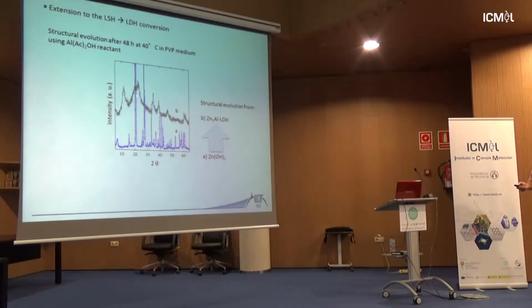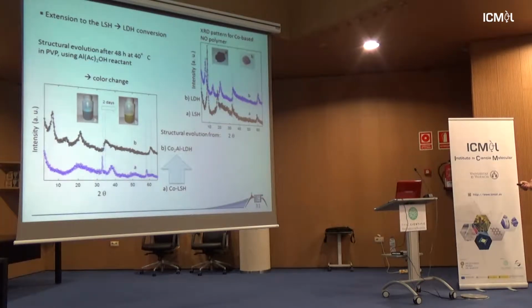So working with zinc in PVP, polyvinyl pyrrolidone, we change the medium. We end up with zinc dihydroxide at T0, versus time zinc aluminum again, because of the aluminum's poor reactivity, but still evolving in time and at 40 degrees C. We have been working with other compositions, cobalt, using cobalt aluminum, and at first when you do the reaction in PVP and using the same reactant at the same temperature, you end up with LSH, and in time you end up with cobalt aluminum.